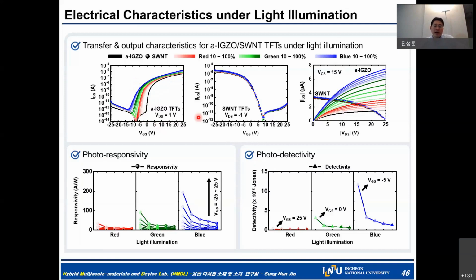Moreover, for the p-type carbon nanotube, fully different behavior was observed. The insensitivity of the light response was achieved due to the very strong binding energy in the carbon nanotube, which comes from the low dimensional carbon nanotube property. So with this kind of load-oriented scheme, we fully implemented the red, the green, and the blue, and the different responsivity here. Photodetectivity we also achieved according to different wavelengths here.